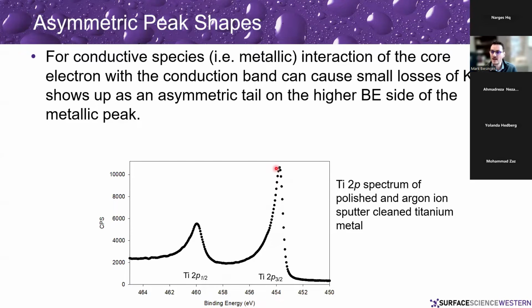And so you have to take that into account when you do your curve fitting. You have to fit this with an asymmetric peak shape. You don't put a Gaussian here and another Gaussian here and another Gaussian here and say, okay, I've got titanium metal, titanium 2, titanium 3, etc. You have just titanium 0 and this asymmetric shape. So you have to take those things into account when you're doing your curve fitting.